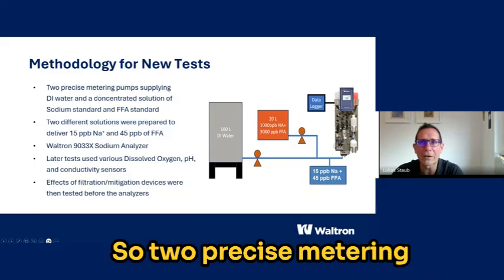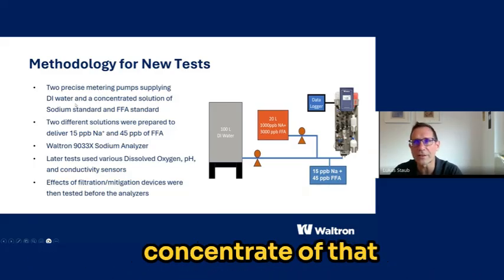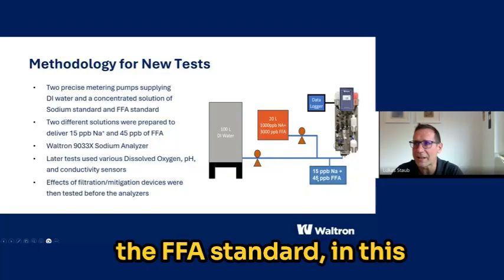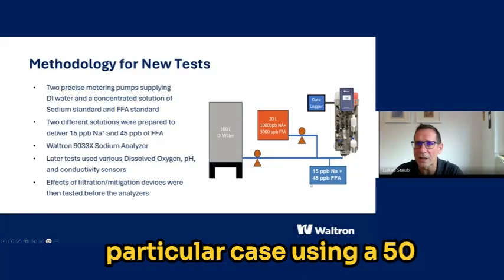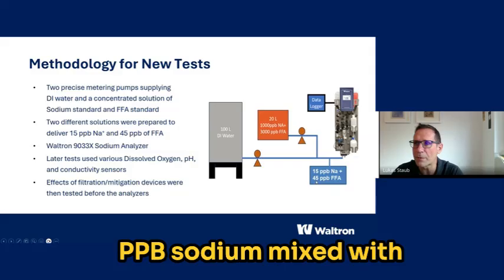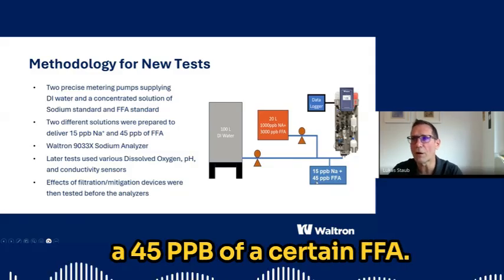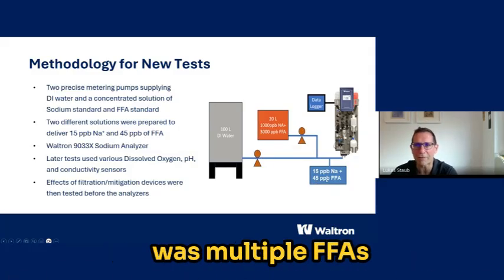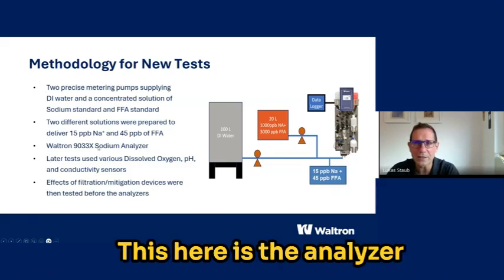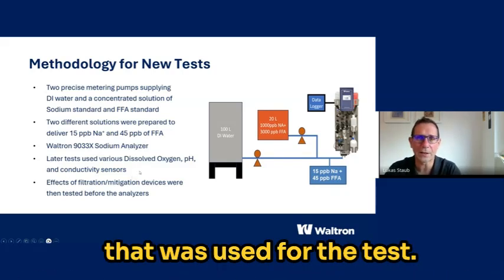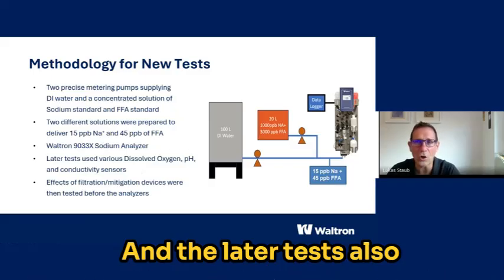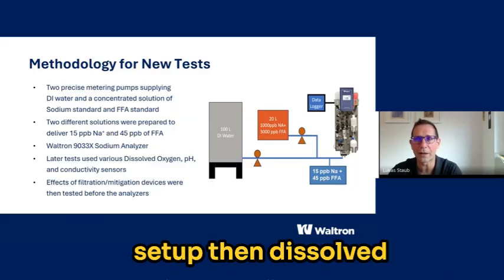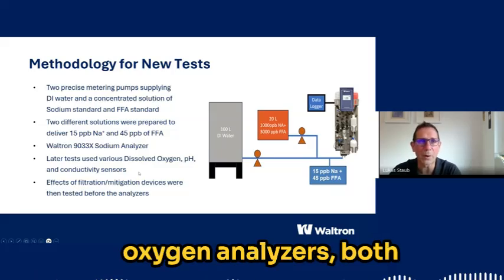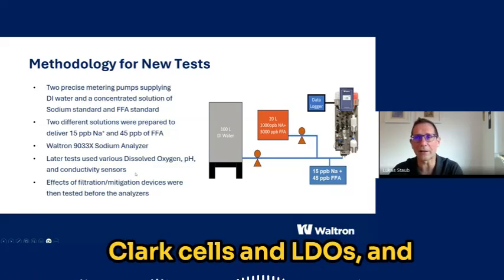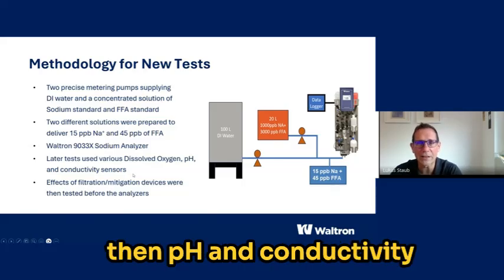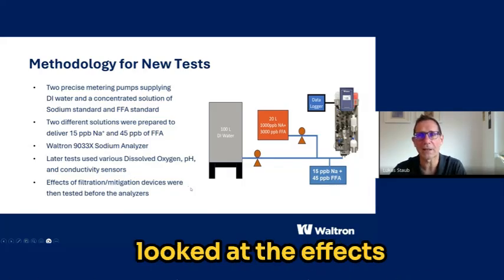So two precise metering pumps are supplying DI water and then the concentrate of that sodium standard and the FFA standard, in this particular case, using a 15 ppb sodium mixed with a 45 ppb of a certain FFA. Actually, there were multiple FFAs that were tested. This here is the analyzer that was used for the test, and later tests also used in the very same setup dissolved oxygen analyzers, both Clark cells and LDOs, and then pH and conductivity sensors where we looked at the effects that this might have.